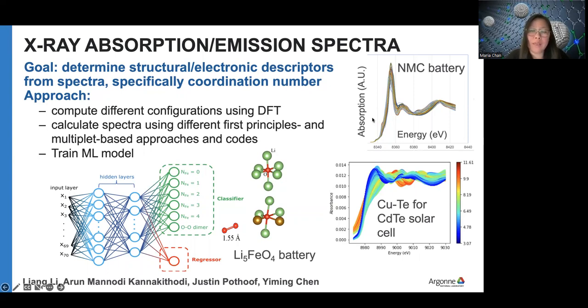In some other cases, we look at transition metal oxide, traditional lithium battery materials, and look at the number of lithium neighbors for the transition metals. That tells you a little bit about the local state of charge, which is useful because when a lithium battery charges and discharges, it's not always even. If you can do mapping and deduce local state of charge, that will be interesting.